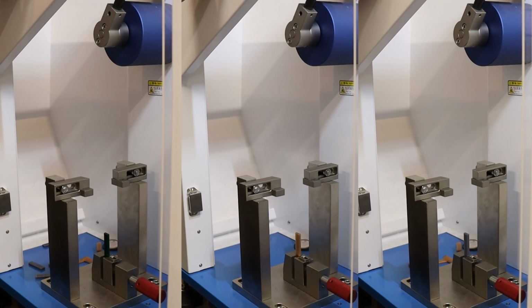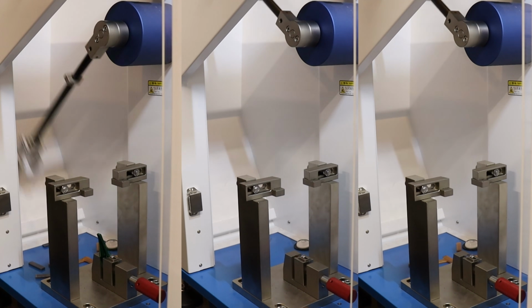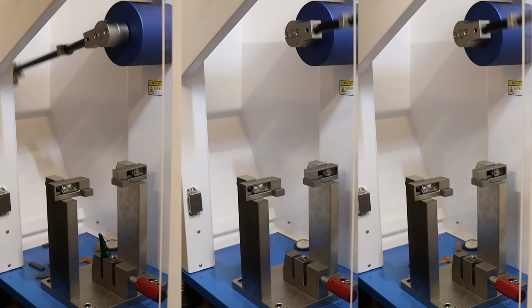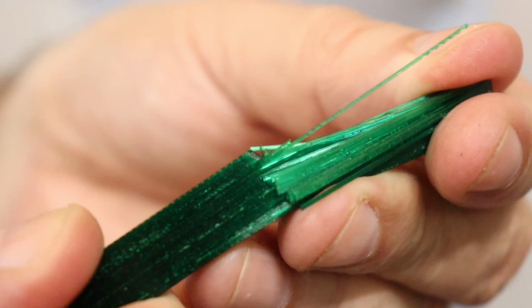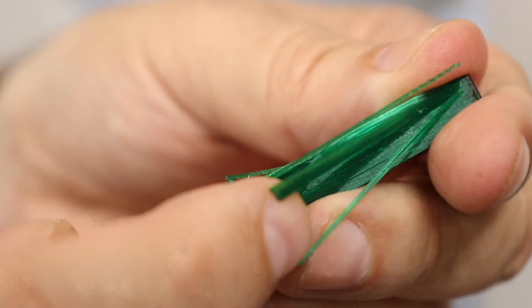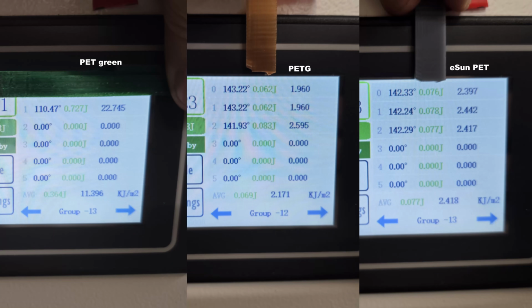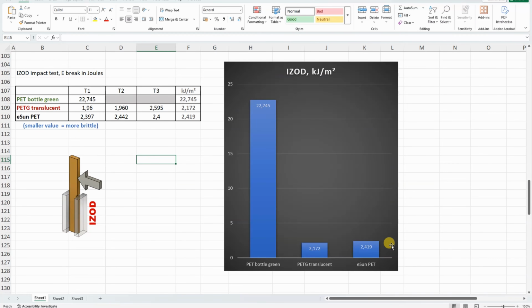IZOD impact test, side by side all three. Not really a typical break in this test, a result of the weaker wall adhesion. And the results, but let's see them on the graph. These two are very brittle materials, but look at this green PET. It looks like a very tough material, better even than ABS.